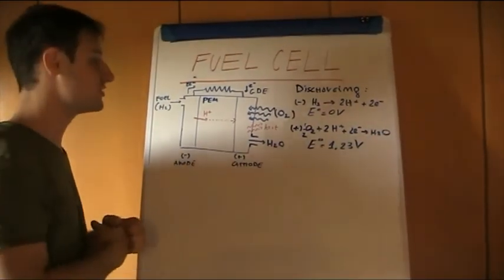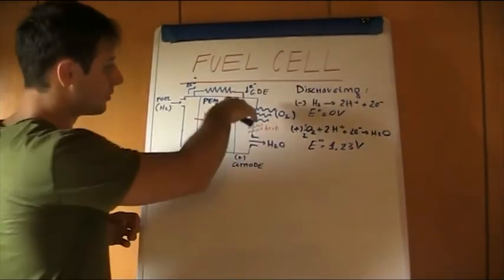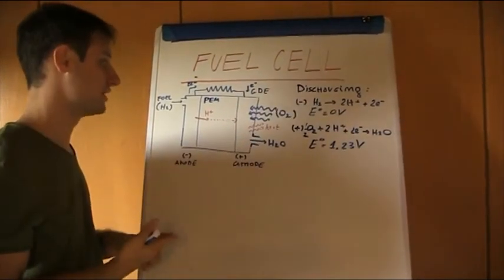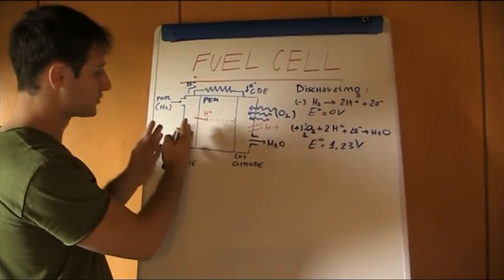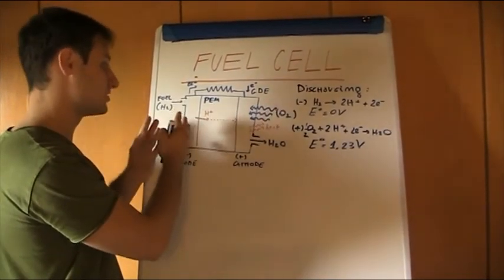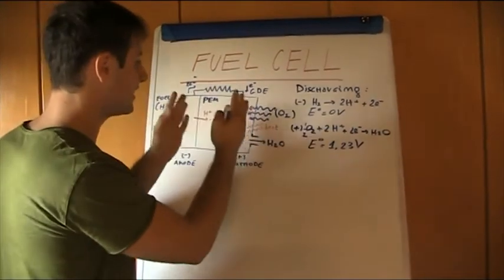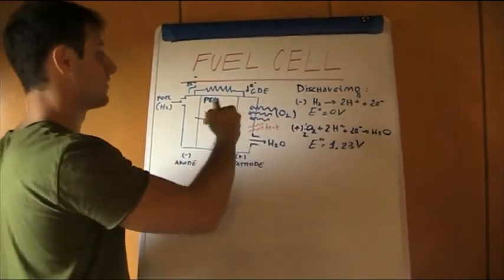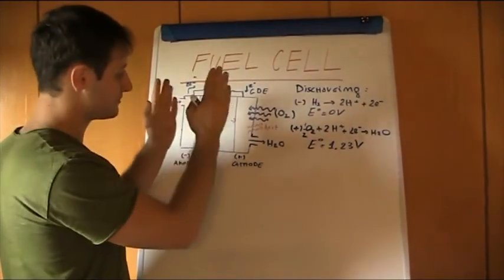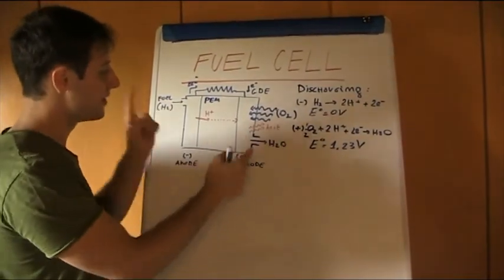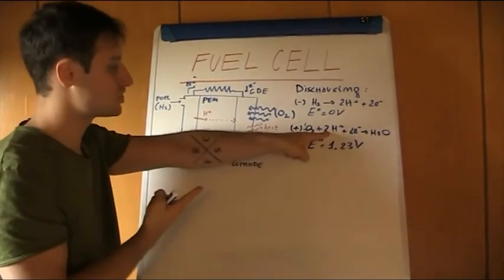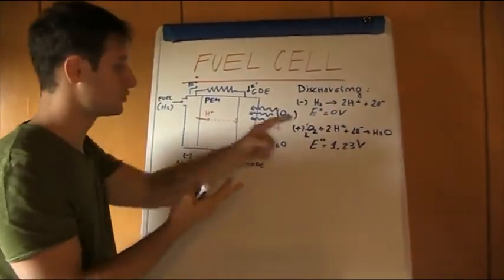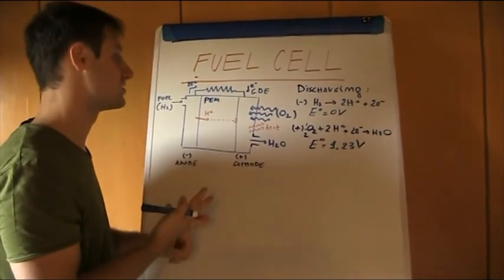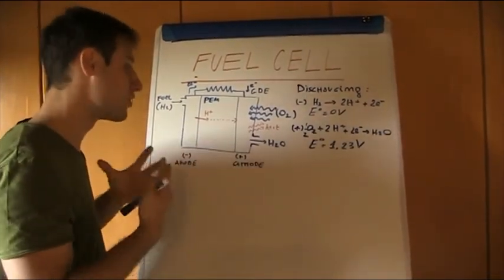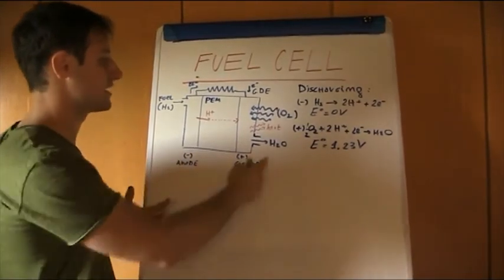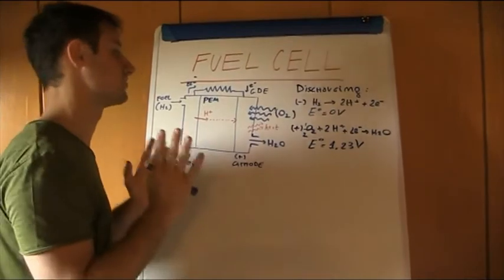And this is the reason why it's so important to define all the components of the gas diffusion electrode. Here we have only a porous electrode containing platinum particles. Here we have a real gas diffusion electrode, because oxygen is taken from the outside, and so we have well-specific features. We have a Teflon binder, we have Nafion in order to ensure the passage of these cations, we have carbon matter in order to ensure the conductivity, and we have this amorphous, porous structure that can promote the passage of oxygen. So this is extremely important.